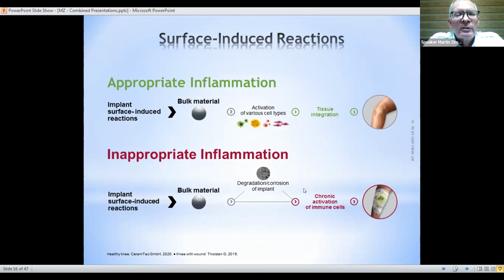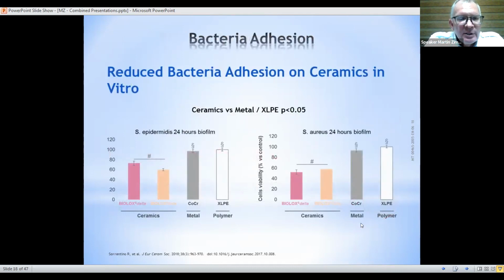And again, as I summarized on the top in green, what we would like to achieve is tissue integration, and what we want to avoid is chronic activation of immune cells, leading to typically this kind of infection. In order to analyze that, a study has also been done in vitro to measure the bacterial adhesion on the surface of different materials used in orthopedics. As you can see here, two staph strains have been used, Staph epidermidis on the left-hand side and Staph aureus on the right-hand side. In these two kinds of bacteria, we can demonstrate that on the surface of the ceramic, Biolox Delta and Biolox Forte, we have statistically less formation of biofilm and reduced thickness of the biofilm, compared both to metal and to polyethylene.